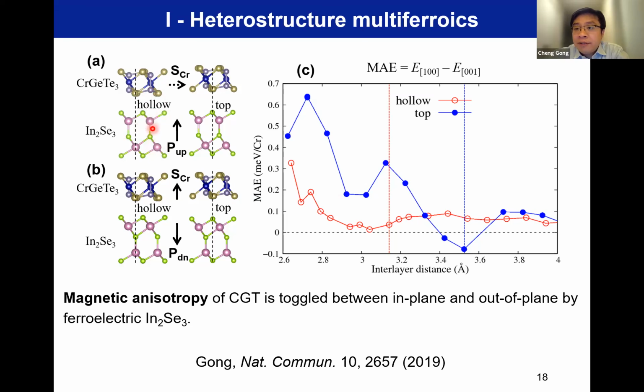So this DFT paper indeed showed when we flipped the ferroelectric polarization of indium selenide from up to down, and that links the in-plane ferroelectric order as well. But here we are only talking about the out-of-plane order, so up and down. Actually, the magnetic anisotropy of this 2D CGT is toggled between in-plane and out-of-plane. So that's not a small change. It totally toggled the anisotropy.